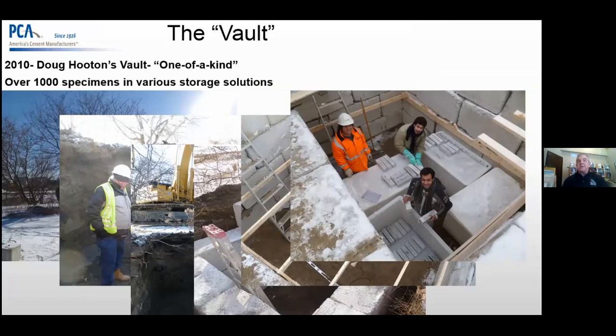And he has several different specimens. And this went on in 2010. So he's got specimens in there that are in calcium chloride solution, sodium sulfate solution, and magnesium sulfate solutions. Doug is a big durability expert on sulfate deterioration and damage, alkali silica reactivity too, but that wasn't conducted here. Doug wanted a long-term storage site, so we provided it to him. The only thing we need to do every year is bring the loader and the forklift out and bring these specimens in once a year. Doug has his students measure them and they put them back in. So we got specimens that are 0.4, 0.5, 0.6, 0.7 water cement ratio, different levels of fly ash and slag, and in different storage solutions, and it's one of a kind.